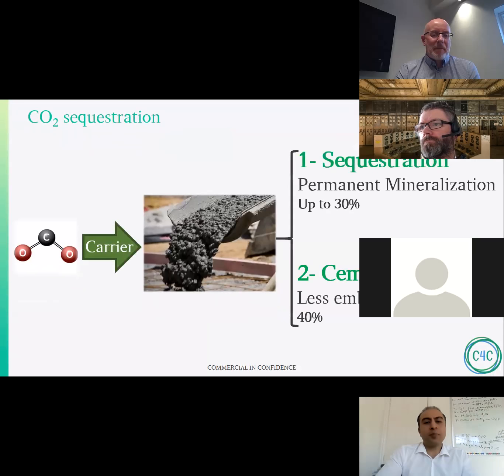Yeah, that's all right. So basically, the technology and selling point of this technology is about the carrier. We are developing a specific polymer-based carrier that we can load with CO2 and then mix with fresh concrete. As a result, we permanently can mineralize a significant amount of CO2 inside the concrete. As a result of carbonation, the strength of concrete will increase, which means we can use less cement. And as we discussed, cement is one of the major sources of CO2 emission. Using less cement means that we are reducing the concrete carbon footprint.